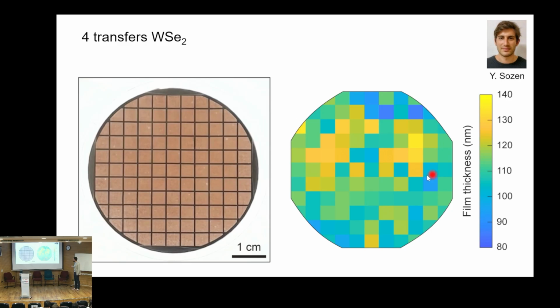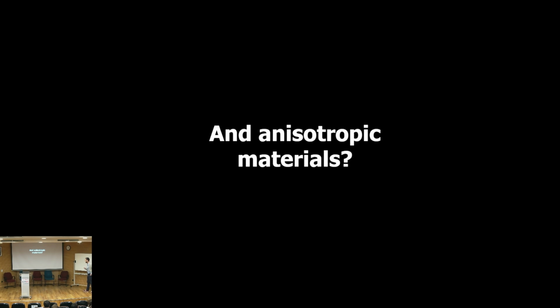So we have done this optical characterization of the film thickness, and over a full wafer, you see that there are, of course, variations in the thickness, but the average thickness is rather homogeneous, okay? So, taking into account the stochastic process of this roll-to-roll mechanical exfoliation process.